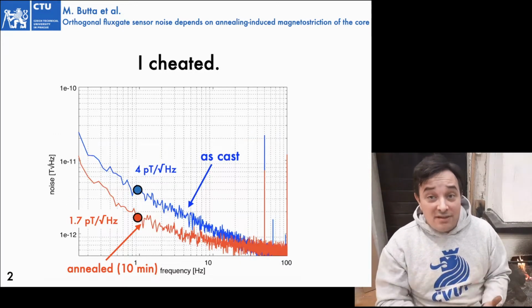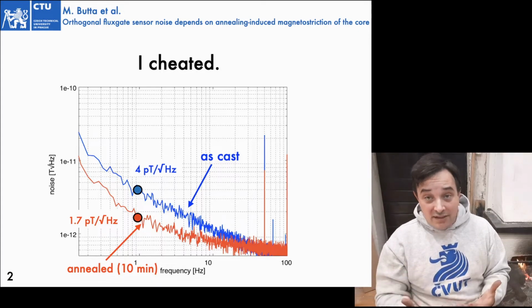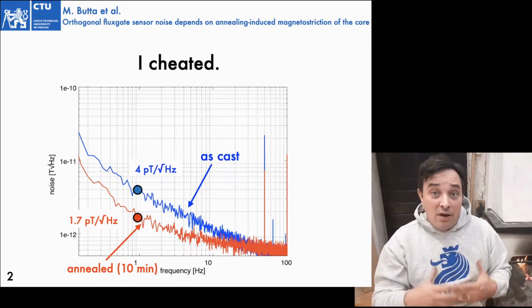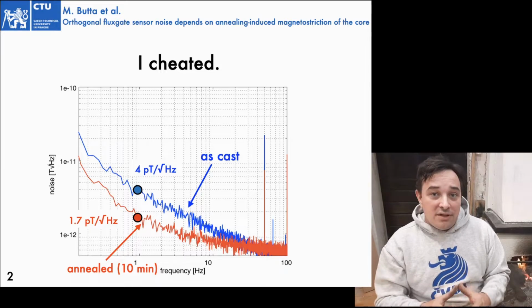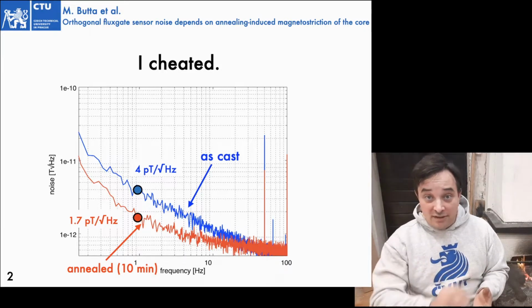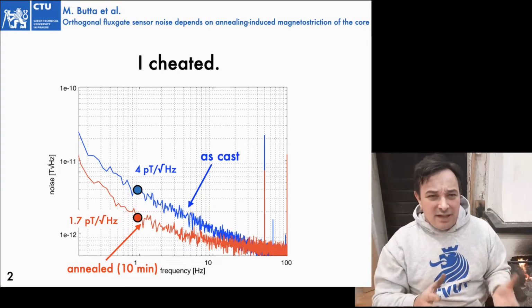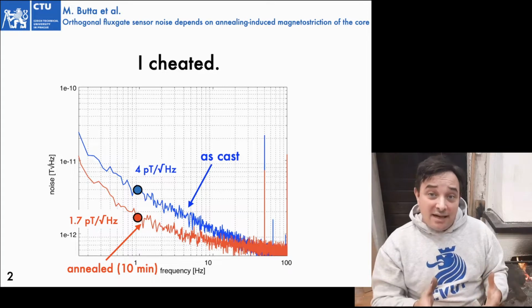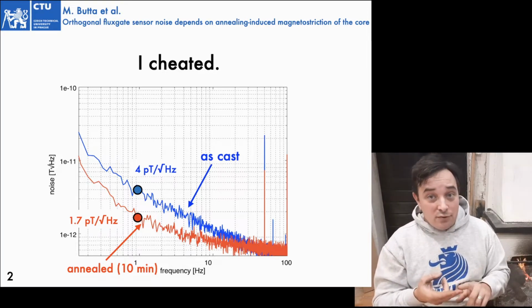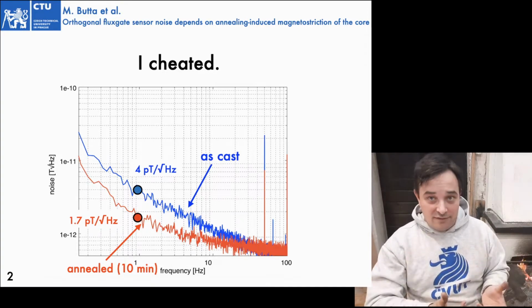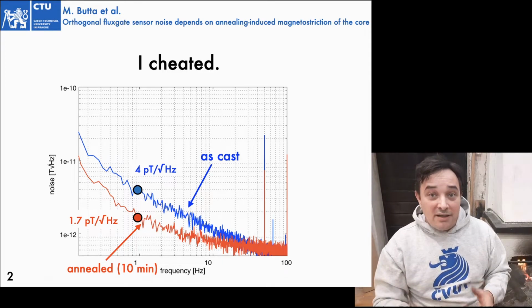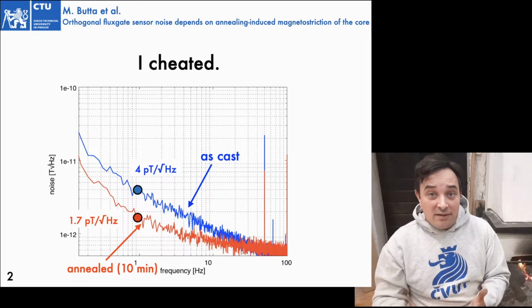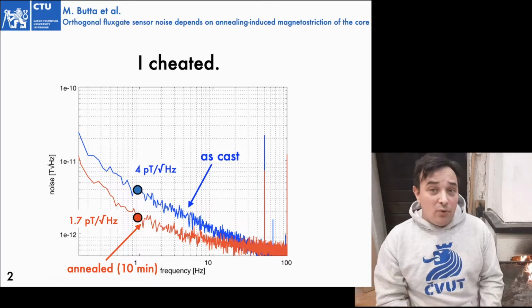And this method was very simple. You have to increase the circumferential anisotropy of the magnetic wire using Joule annealing. You inject a current in the wire, kind of 370 milliamps, and this current has two roles. The first one is to create a circumferential field, and the second one is to warm up the wire to perform the annealing. And this system works pretty well.